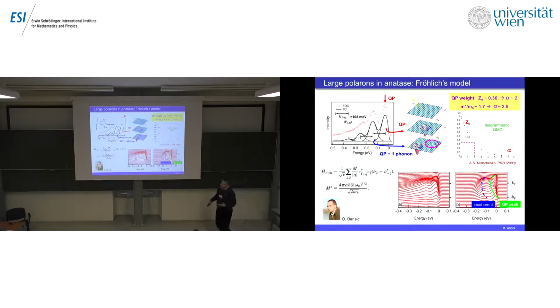Now, how can we determine the strength of the interaction? Well, we have looked up in the literature this diagrammatic quantum Monte Carlo result, and there are two indicators. One is the quasi-particle peak. We can measure this intensity relative to the whole spectrum, and we have something like 0.36, and in this calculation, this tells you that alpha is about 2. Or we can look at the mass renormalization, 1.7, and in the same calculation, one would get 2.5. I mean, we don't claim to be more accurate than this, but this tells you essentially that the interaction is moderate, and we can think of the system as a large polaron, actually.